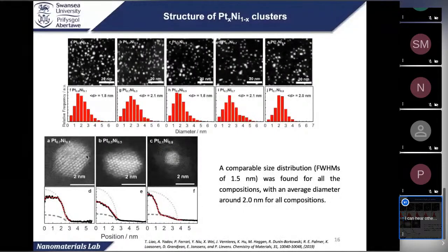So here, we produced platinum nickel with 5 different compositions. From the top, you can see there's Pt 0.9 nickel 0.1, and all the way to platinum 0.1 nickel 0.9. On the bottom left, you can see 3 examples of high magnification STEM images. On the platinum-rich cluster, the structure is more like pure platinum, but you have some tiny cores with nickel-rich areas or domains.